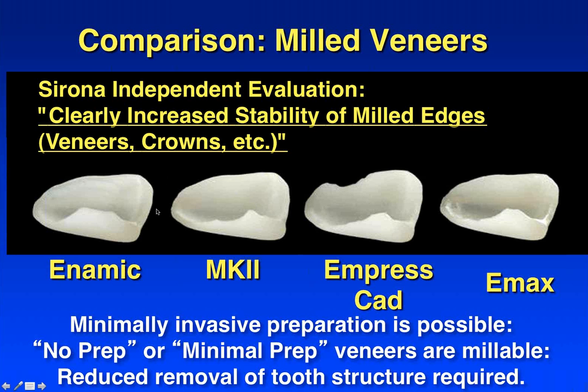Another demonstration is when we mill out veneers with Enamic versus Mark II, Empress CAD and Emax. You can clearly see the chipping that occurs in all the traditional ceramic materials, whereas you don't see that for the Enamic. You can make very thin veneers, essentially no prep veneers, milling Enamic on the Cerec system, whereas obviously you can't do that with any of the traditional ceramics because it just gets too thin and it chips severely.